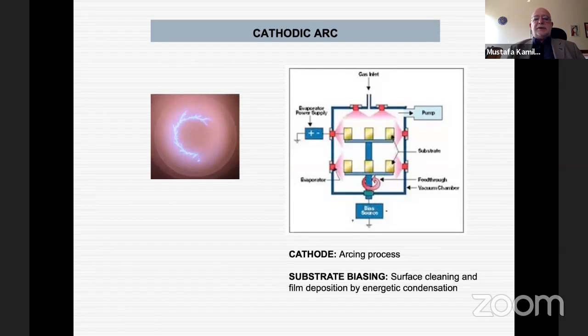So as you see on the left, this is a cathode surface when this arc is burning on it. So you see this blue lightning light movement is the movement of the arc on the surface. While this arc is moving on the surface, it melts and evaporates the material, and it is converted into a very strong plasma. And since this is being produced in vacuum, we can control the environment for production of different compounds by introducing several reactive gases into the environment, such as nitrogen, methane, etc.